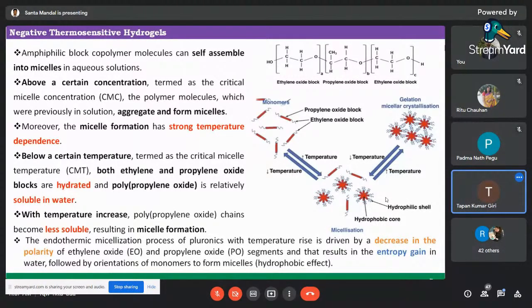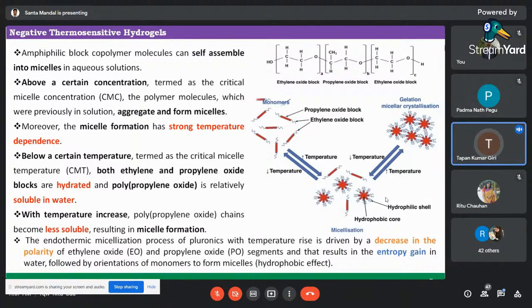One is the minimum concentration of the polymeric solution, and also the minimum temperature required to change the solution form to the hydrogel formation, meaning the micelle formation. So above a certain concentration, termed the critical micelle concentration, the polymer molecules which were previously in solution aggregate and form micelles. Moreover, the micelle formation is strongly temperature dependent. Below a certain temperature, termed the critical micelle temperature, both ethylene oxide and propylene oxide blocks are hydrated, and propylene oxide is relatively soluble in water. With temperature increase, polypropylene oxide chains become less soluble, resulting in micelle formation.